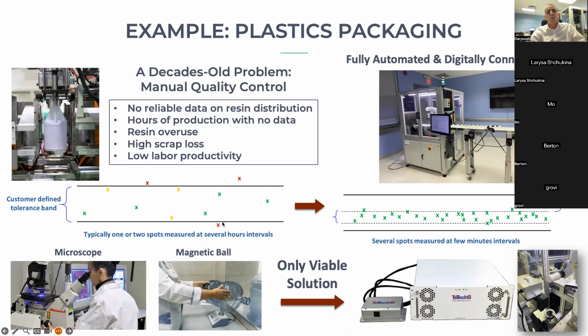So basically, the only viable solution to such a problem is using a terahertz time domain measurement system. And of course, it has to be built into an automated solution. Once that is applied, one can take a lot more measurement data and tighten the tolerance range. So basically, you end up even saving the resin, especially the expensive resin, for the production line.